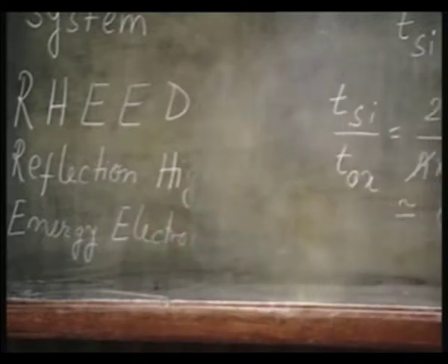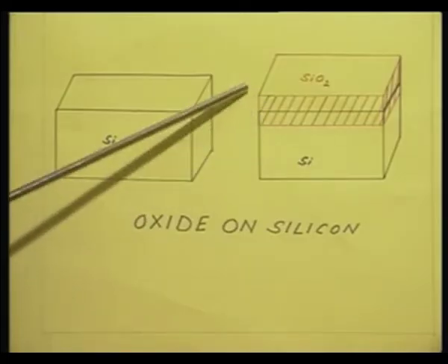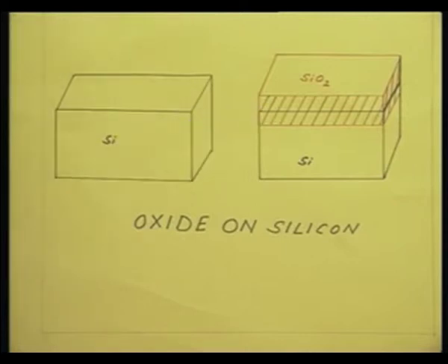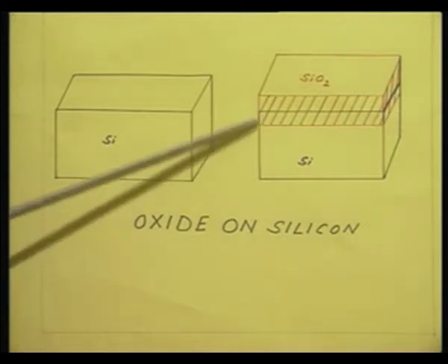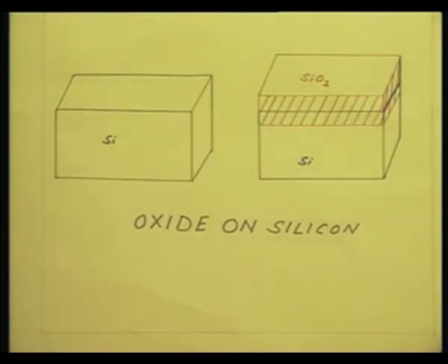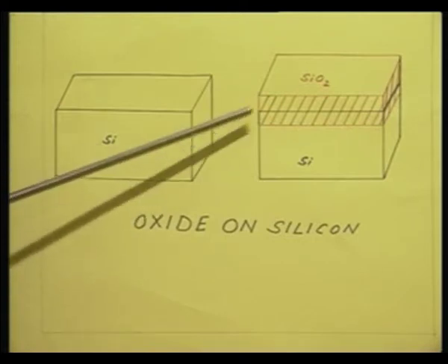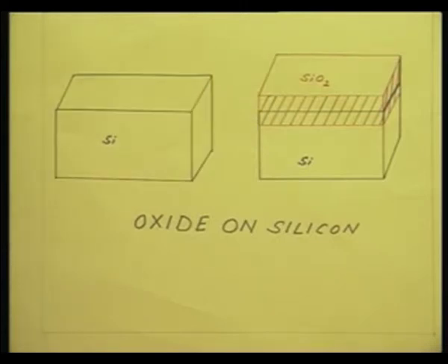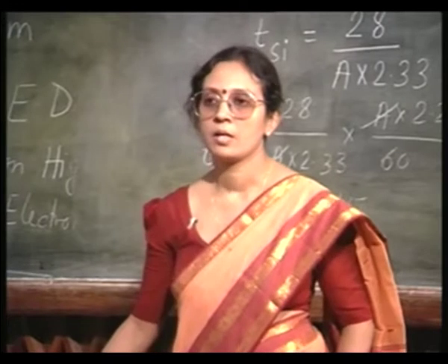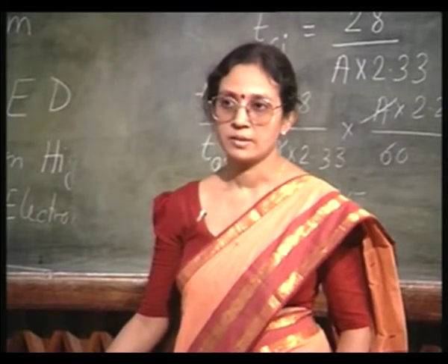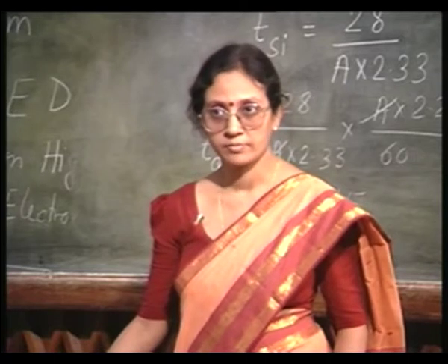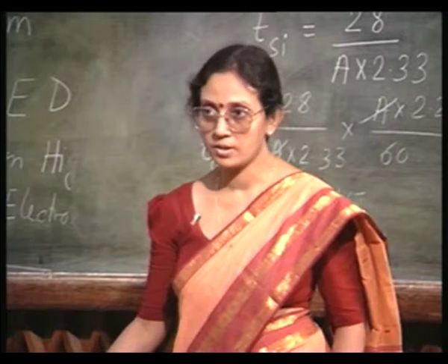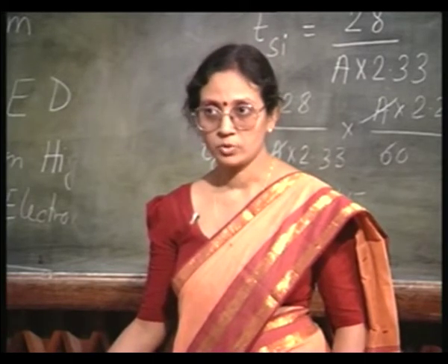That is, looking at this figure once again, if the total width of the red hatched area is 1000, 450 is below the black line and 550 is above the black line. Below the black line is the region of silicon that is consumed. So, 450 angstroms of silicon have been consumed and 550 is above the original surface. That is why, if you form an oxide and then selectively etch it, you will get an indentation on the surface itself. That is because some part of silicon was consumed wherever the oxide is formed. Okay.